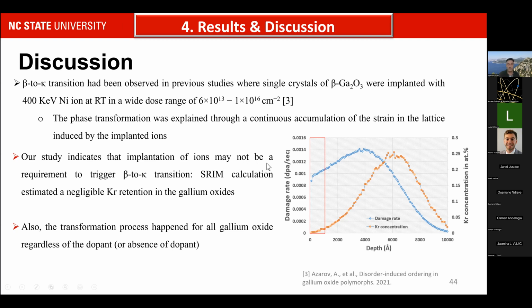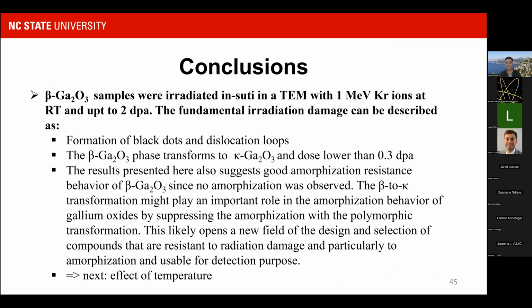indicates that implantation of ions may not be a requirement to trigger this transition. Because in fact, if we look at SRIM calculations, we select our ion energies so that they are not implanted. We just want them to go through the sample, and we have extremely small retention, less than 2% throughout the sample. They induce the damage, but they go through, which means that this theory about implantation of ions need not be invoked to explain the phase transformation. And the other interesting part that we need to look at as well is the effect of the dopant. It doesn't seem to have any effect in terms of the phase transformation.